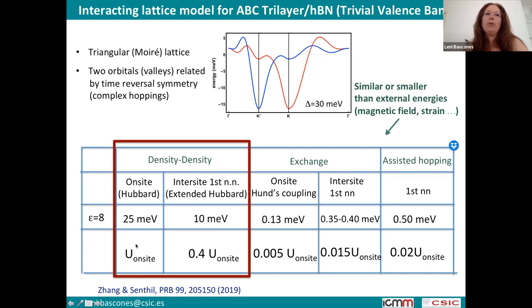So there is the so-called Hubbard interaction that is of the order of 25 millielectron volts. The intersite one is also large. And then there are several other terms, like the on-site Hund's coupling, the intersite first neighbor, and even other terms like assisted hopping, which are much smaller. So somehow it looks like these terms are the most important ones.